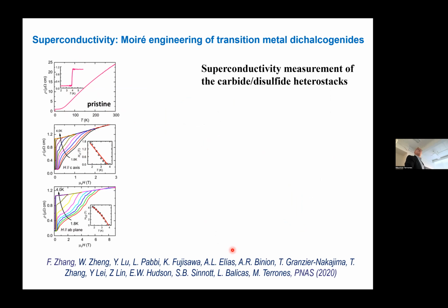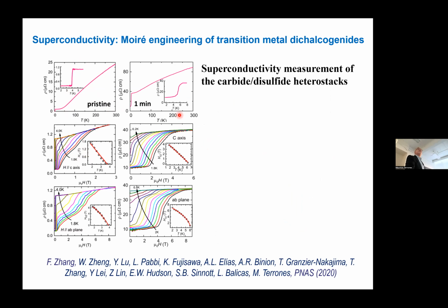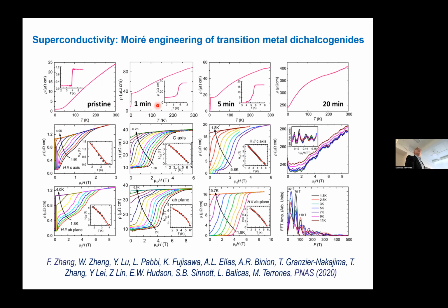One thing that we saw is that after 1 minute, the transition was close to 7 Kelvin, and it was still a superconductor. It didn't go all the way to 0, but it went down, right? So we have a transition. And 5 minutes was still around 6 Kelvin, and then at 20 minutes it was still metallic, and up to 2 Kelvin we couldn't see a superconducting transition. But I think that might happen at even lower temperatures. Maybe that's what will happen. But this is a good metal as well.